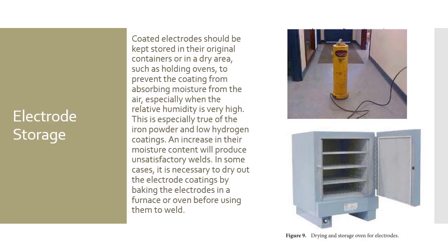Coated electrodes should be kept stored in their original containers or in a dry area such as holding ovens to prevent the coatings from absorbing moisture from the air, especially when the relative humidity is very high. This is especially true of the iron powder and low hydrogen coatings. An increase in their moisture content will produce unsatisfactory welds. In some cases, it is necessary to dry out the electrode coatings by baking the electrodes in a furnace or an oven before using them to weld. So we're talking about the 7018 and the low hydrogen electrodes. You can't store them on a shelf in open air because they'll just suck up the moisture.